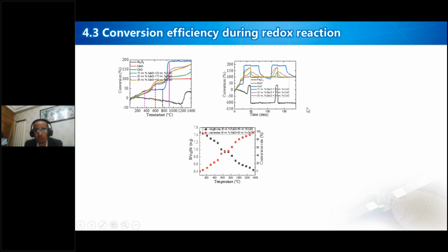The other is the conversion efficiency during the redox reaction. So when we see the conversion efficiency for the charging temperature, for the normal state, which is a stable state, the 50% is in good and stable condition compared to the others. For example, with cobalt, up to 400 it is increasing, but around 450 to 800 it is constant. When you start at 800 degrees, it sharply increases, and from 1000 it goes to a plateau.